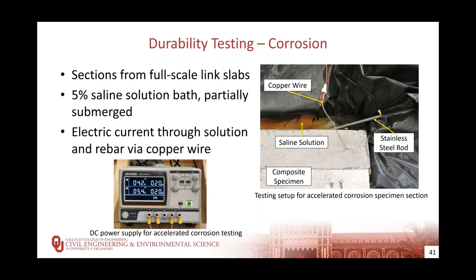All cut surfaces will be epoxy coated to prevent corrosion on surfaces that would not be exposed during service. Now for the corrosion tests, a 12-inch by 8-inch by 6-foot long section will be removed from each specimen with the cuts perpendicular to this link slab. We'll make sure a copper wire is part of each specimen, and all sections will be placed in a shallow pool of 5% saline solution.